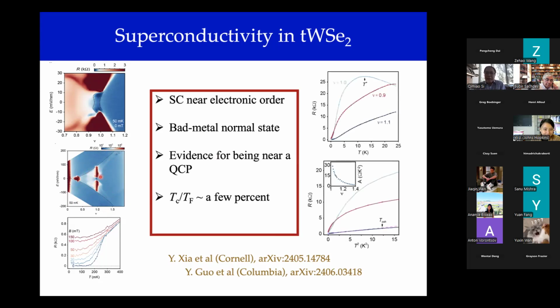That's exciting. But there's a slew of other features that make this experimental observation, in my opinion, particularly exciting. So one is that the normal state is a bad metal. If you look at the sheet resistance versus temperature at this half-filling case, nu equals 1, it reaches a value which tells us that k_F l is of order unity. And so we have a bad metal there.